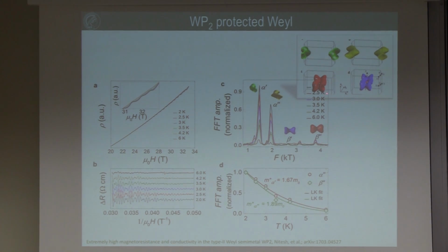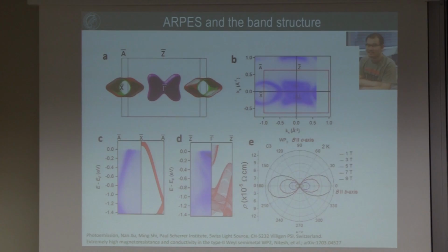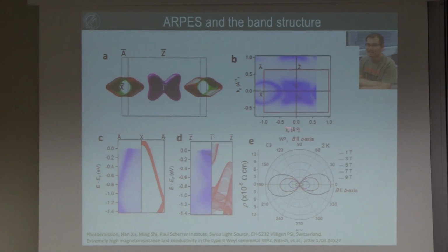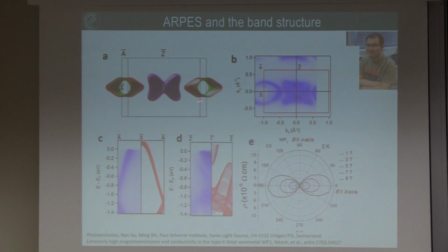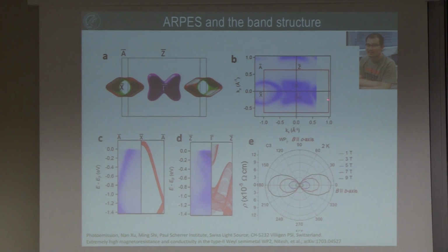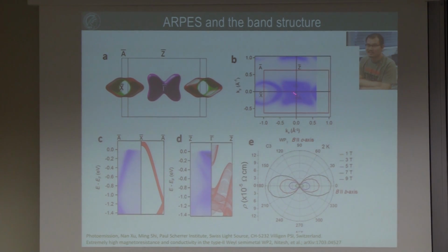And here are still the data from WP2. So what we do, again, in all the semi-metals, you see nice quantum oscillation. You can then assign the oscillation to the Fermi surface. And similar to palladium cobalt O2, we have here an open Fermi surface, highly anisotropic open Fermi surface, and we have some more closed pockets. So we already got ARPES data from the PSI, which shows really nicely that the Fermi surface which we calculate is in nice agreement again with the band structure, which means, okay, here the single particle picture works.